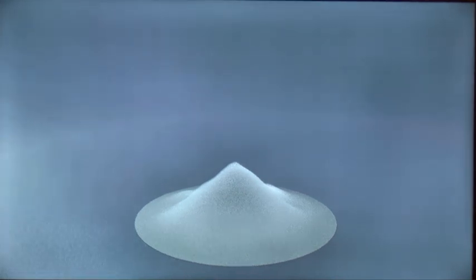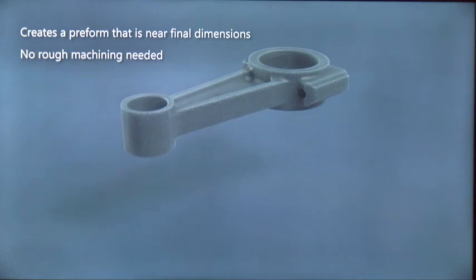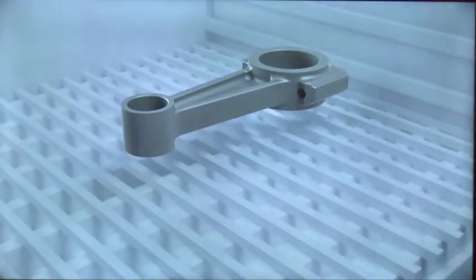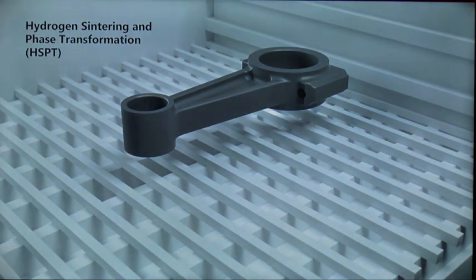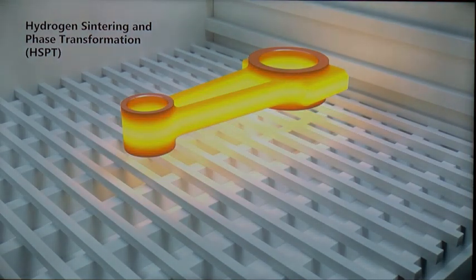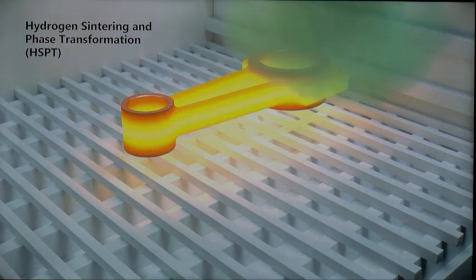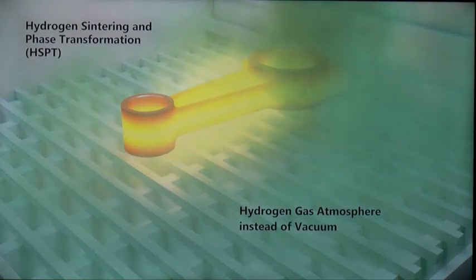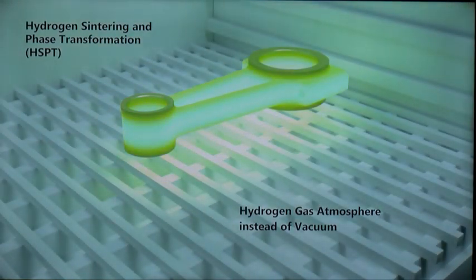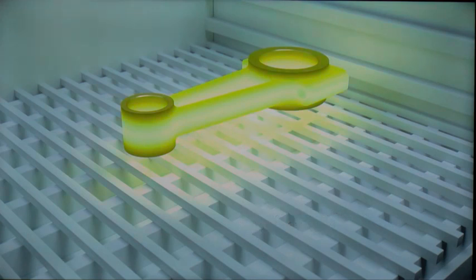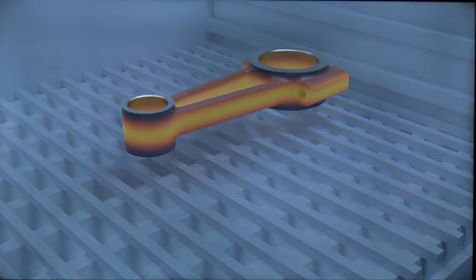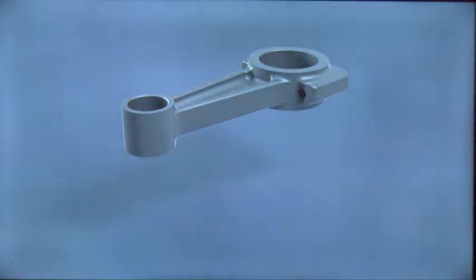So with our process here, we have a similar near-net shape manufacturing process. So we can get that same advantage of having material that's the same shape and the same size. We sinter it, as you can see here, and then we introduce hydrogen gas while sintering it. Now this is what we basically call a beta stabilizer. It's a temporary alloying element is what hydrogen is, but it stabilizes the materials in there and it allows you to make finer grains on that.